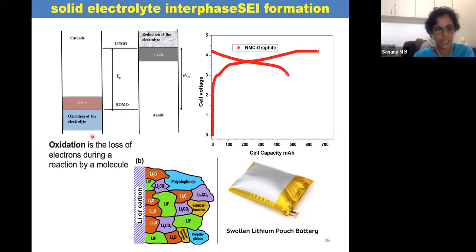Basically, oxidation is a loss of electrons during the reaction. So there is a loss of electrons from the electrolyte. Now for that, what we call is the formation cycle. For a stable lithium ion cell, the chemical potential of the anode should be lower than the LUMO of the electrolyte, and the chemical potential of the cathode should be higher than the HOMO of the electrolyte. If that doesn't happen, the electrolyte dissociates, either undergoing oxidation or reduction. So during the first cycle, that is what we do. We oxidize and reduce the electrolyte, and a very thin layer called the solid electrolyte interphase, usually called the SEI layer, forms on the graphite side or the anode side.